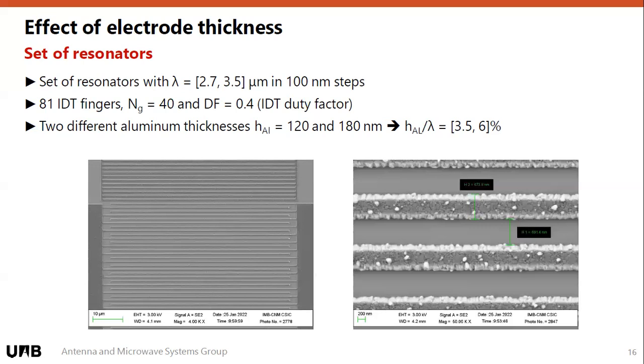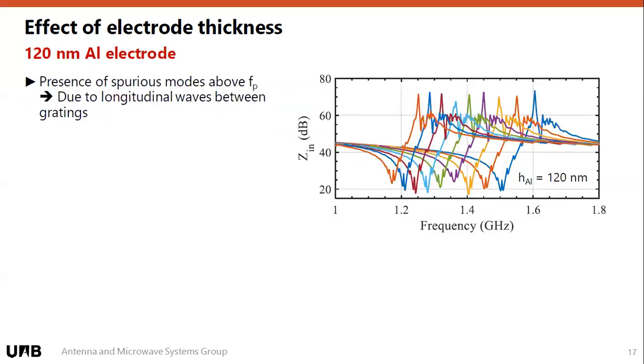And then we built the same structure using two different aluminum thicknesses, 120 nanometers and 180 nanometers. This is an important measure in terms of the thickness of the electrode to lambda ratio, 3.5% and 6.5% in this case. There are studies that have shown that you have an optimal, as we will see, at around 6 to 10%. There are many studies around this, but they vary in terms of which aluminum they are using, which is the process they are doing. So we don't dive into that. What we're going to see is that we measured the 120 nanometer resonators, and we obtained these measurements here.